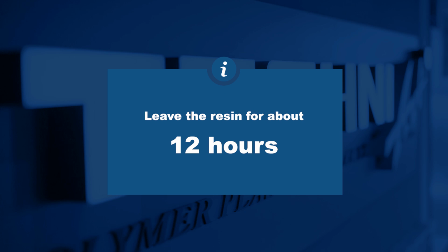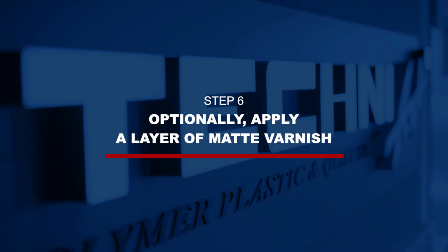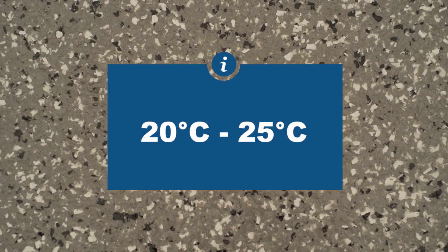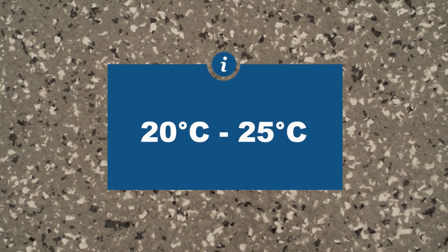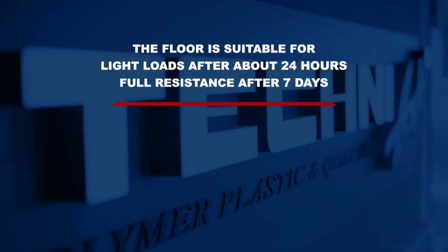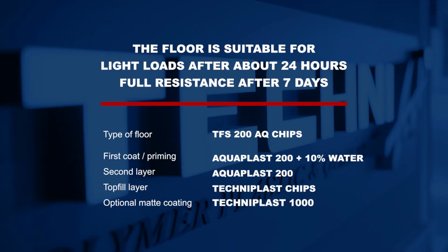After covering the entire planned surface, leave it to bind the resin for about 12 hours, and then optionally, you can start applying the matte varnish. Provided that it is cured at a temperature between 20 and 25 degrees Celsius, the floor is suitable for light loads after about 24 hours and obtains full resistance after 7 days.